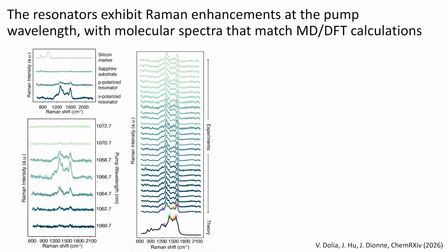And then, since I mentioned Raman spectroscopy, this is probably one of the more detailed plots I have, but all you have to do is take away the fact that if you are not illuminating on resonance, or if you don't come in with the right polarization of light, you're not going to get any signal, right? Because Raman spectroscopy is so weak. But we engineer these nano antennas in such a way where they can strongly amplify or enhance that Raman spectroscopy signal. And then when we look at different sensors, in this case, all different sensors, but all with the same molecule, you can see basically we're getting that same Raman enhancement.